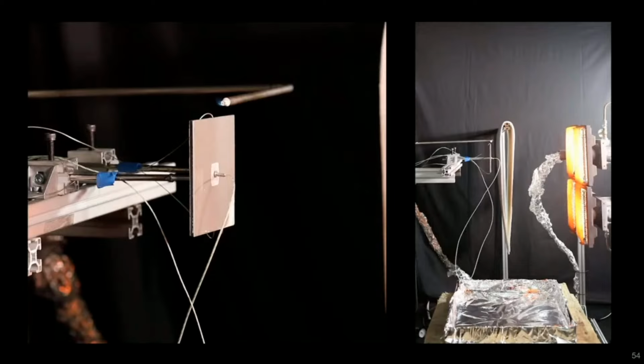Just a few seconds later, the front aluminium facer will completely fall away from the sample and land, whilst burning, in the debris tray. The rear aluminium facer, which is restrained on the holding rods, will remain in place, and it will stay mounted on the sample holder, as will the majority of the polyethylene core, and that will remain attached to the rear face. Flaming will then continue on the front aluminium facer, now in the debris tray, and discontinuous flames will become visible over the front surface of the specimen.